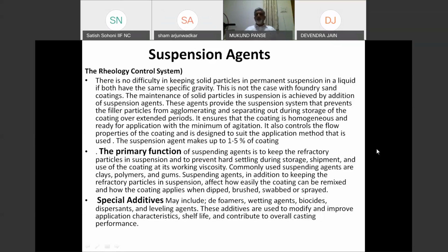The primary function is that it should not allow the paint to settle in storage and shipment, and should not form a hard layer at the bottom. That is, the bench life of the paint when kept in a container should be fairly good. Otherwise, a very hard layer will be formed, and then it will not get mixed with the thinner or alcohol properly. Also, it should be possible to easily apply the coat by brushing, swabbing, or spraying.